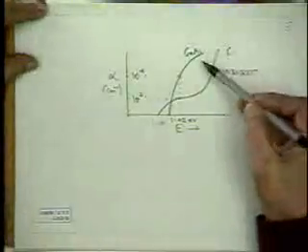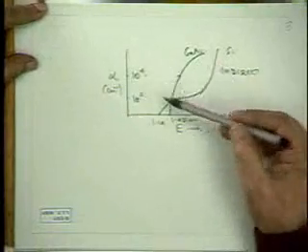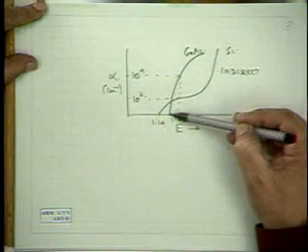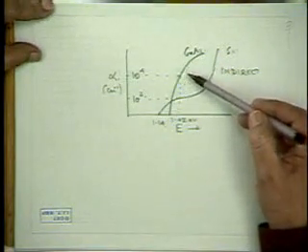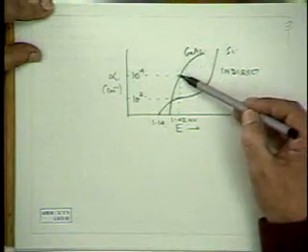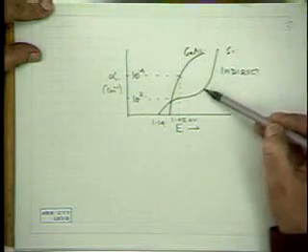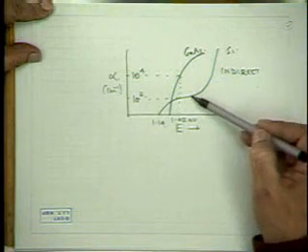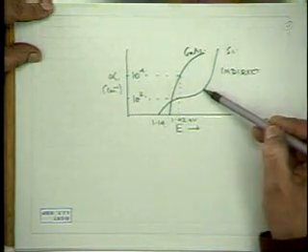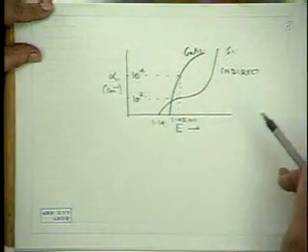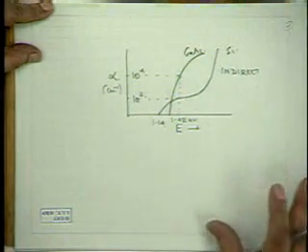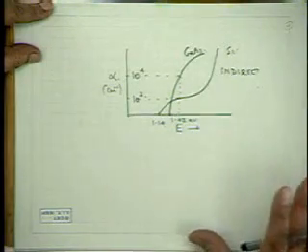we showed that for direct gap semiconductors like gallium arsenide, the absorption rose very sharply at the absorption edge, and the absorption coefficient was proportional to (h nu minus Eg) to the power half, whereas in the case of an indirect bandgap semiconductor like silicon, the absorption coefficient was proportional to (h nu minus Eg minus Ep) to the power 2. Now, in this case, of course, we had two cases: phonon emission as well as phonon absorption.